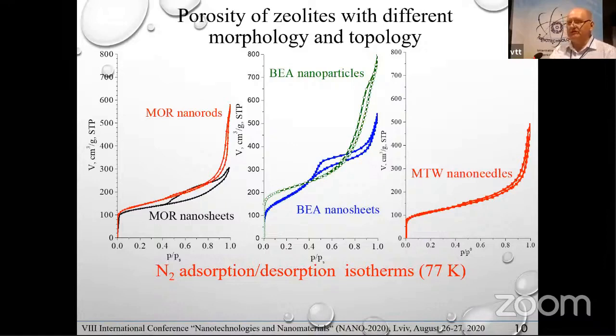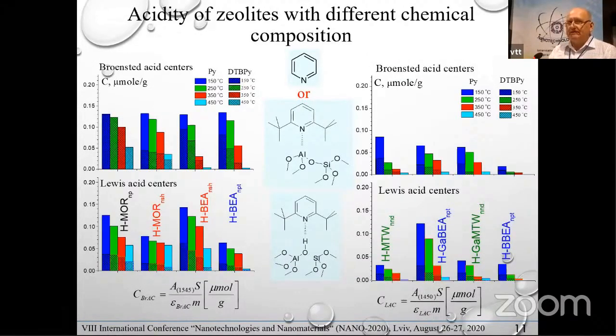Adsorption properties of such materials are very high, because in such materials there are not only micropores but a large volume of mesopores. Adsorption data show the presence of a developed external surface, in some cases up to 600 meters squared per gram. Due to the possibility of ion exchange, such zeolites can consist of different active centers, not only Lewis acid centers, but also, due to ion exchange into hydrogen, into protons, in such structure protonic acid centers can be formed. These are bridged SiOH groups, which have strength similar to hydrochloric acid.